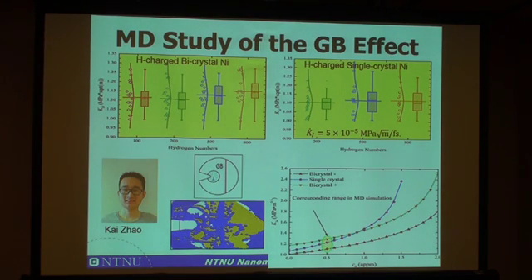You have seen results from my student Kai Zhao. He has used molecular dynamics to probe the effect of grain boundary. Here maybe it's not so easy to see. Vertically is the K1D, the K1 stress intensity factor for dislocation emission, as a function of hydrogen numbers. These hydrogen numbers can be easily converted to the hydrogen concentration.